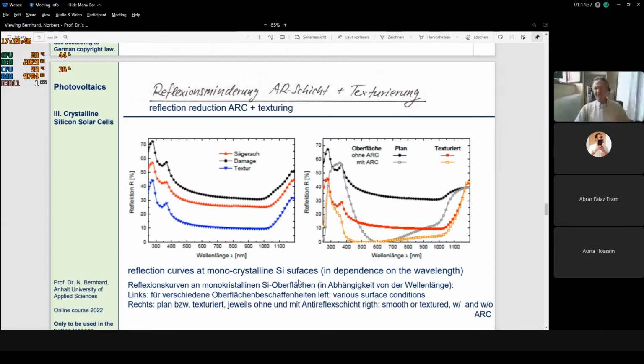If you have the texturing, we have the red curves. The red curve would be the texturing alone, and the orange curve would be the texturing plus the anti-reflective coating. And you see this, of course, is the best performance. That means texturing and anti-reflective coating together achieve the lowest reflectivity. That means the best usage of photons.